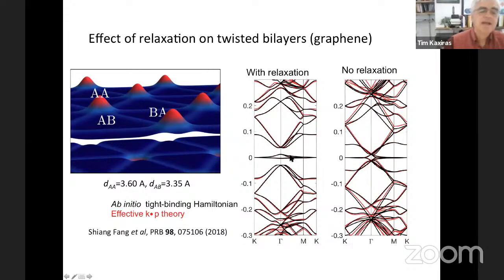The black bands are produced with the tight binding Hamiltonian that I described earlier, using as a basis the localized Wannier orbitals. The Wannier orbitals associated with every atomic site in real space produce these bands in reciprocal space. And this is now the picture that everybody refers to, the flat bands. But as you see again, the bands are never completely flat. There's always some dispersion. And there are gaps separating them from other energies.